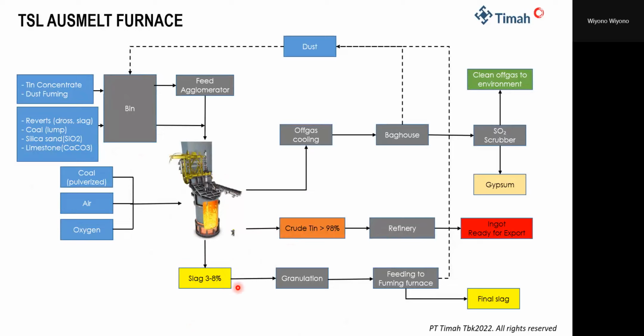The target of output slag in the Ausmelt is to feed into the fuming furnace. In the Ausmelt furnace, we also recover byproducts from the smelting process and the refining process. This is such a dust. This is dust from fuming, and we also charge revert, and then this is circulating dust from the Ausmelt itself.